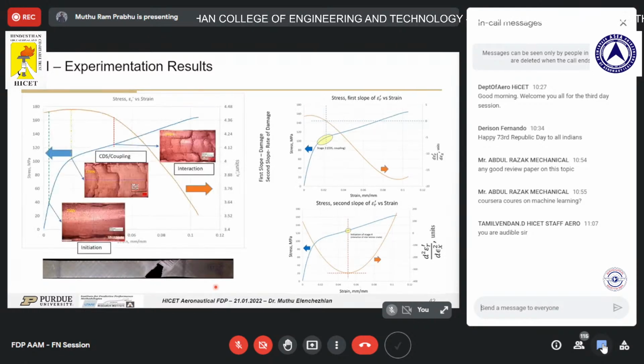And on the experimental side, what I performed was some quasi-static testing of 4-ply off-axis composites. These were tested as per the ASTM standard in MTS. During this, we collected the dielectric data during the quasi-static testing. Based on that, the results that we obtained were, this is the fractured sample, this is the stress strain curve as we showed earlier, and this is the dielectric relationship curve. We obtained the first slope, which is the rate of change of these curves, and again the second slope for this curve, which is the acceleration of the curves.